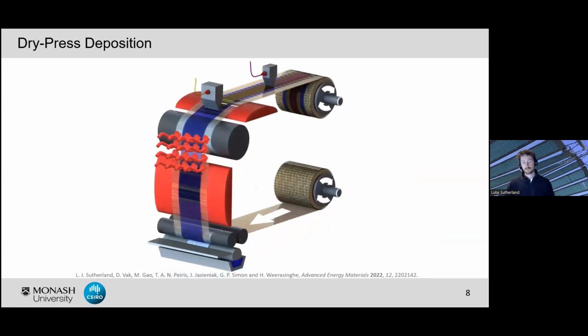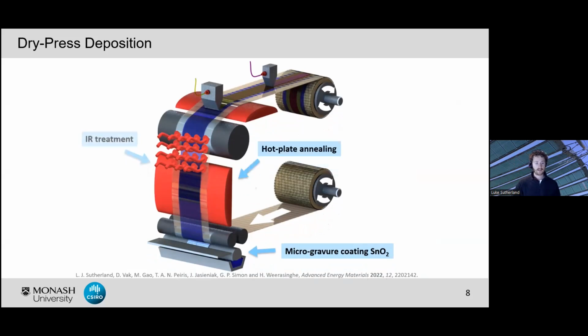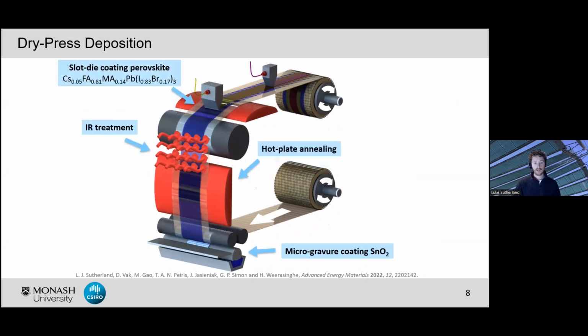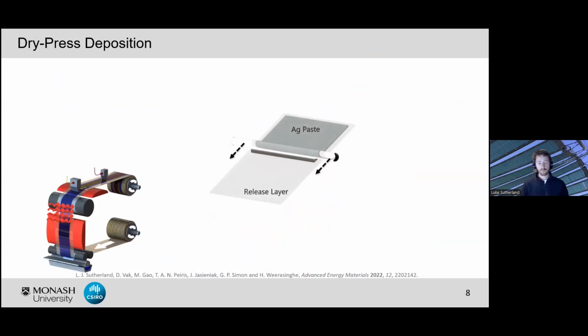And so what we did was we start with the complete roll-to-roll fabrication of our devices up to the HTL. So gravure coating our tin oxide, slot die coating the perovskite, and then slot die coating this spiro as our hole transport layer. We then fabricate our electrode on a separate non-stick release layer substrate. So this is just a PET with, say, a non-stick silicone liner. We then firstly coat a silver paste.